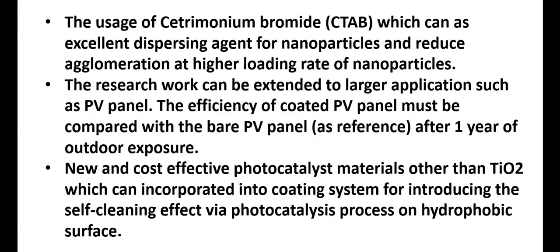So our next research target which we are going to go into is to use CTAB, cetrimonium bromide, which can act as an excellent dispersing agent for nanoparticles and reduces agglomeration at higher loading rates of nanoparticles. So the research work can be extended to a larger application such as PV panel, and the efficiency of coated PV panel must be compared with bare PV panel after 1 year of outdoor exposure. New and cost-effective photocatalyst materials other than TiO2, which can be incorporated into the coating system for introducing the self-cleaning effect via photocatalysis process on hydrophobic surfaces, are also ongoing.